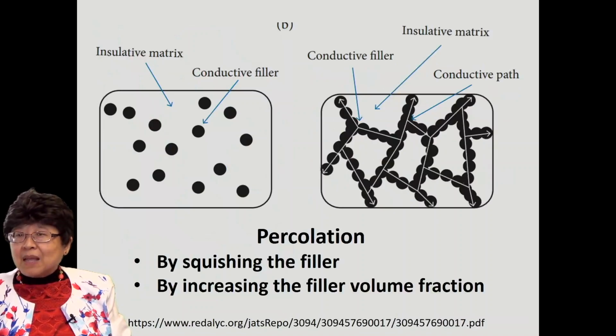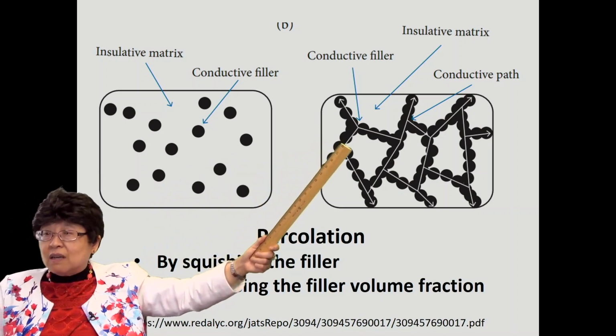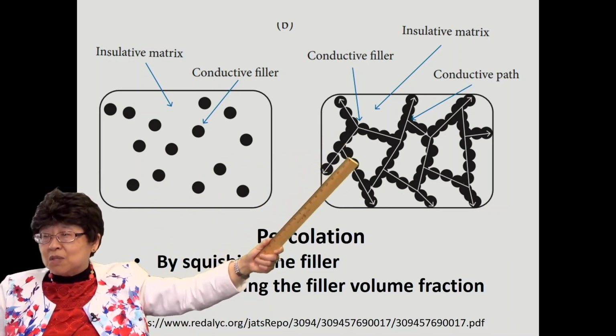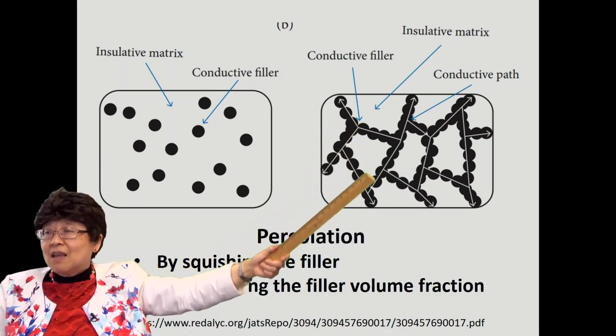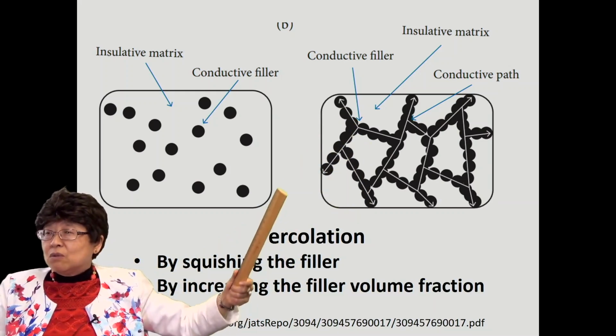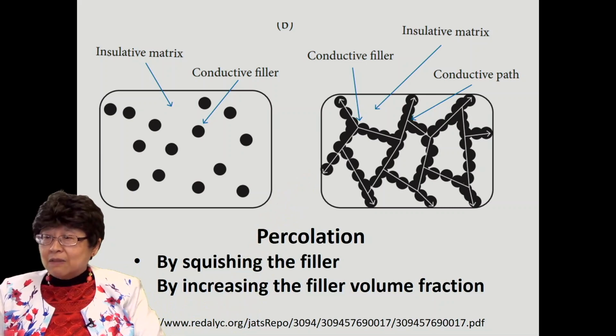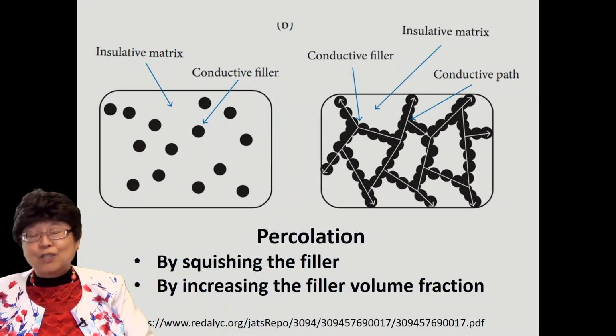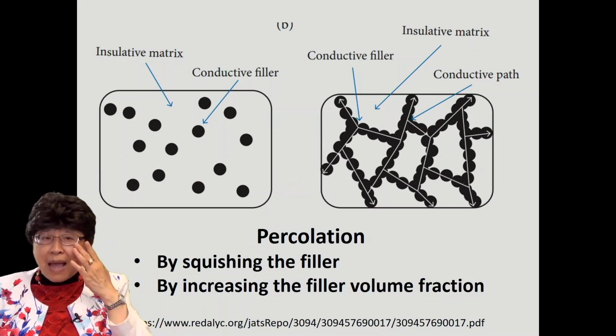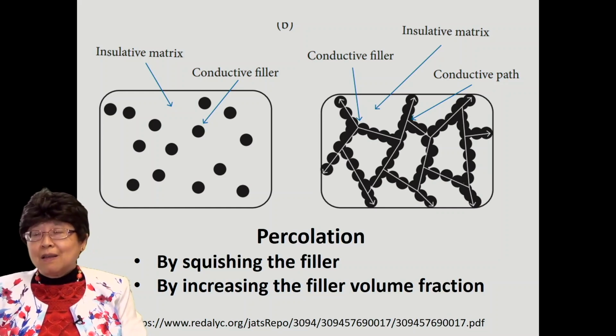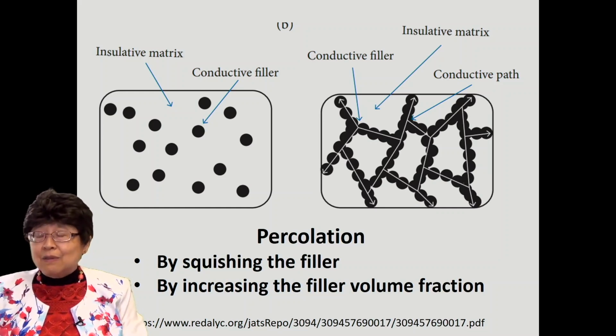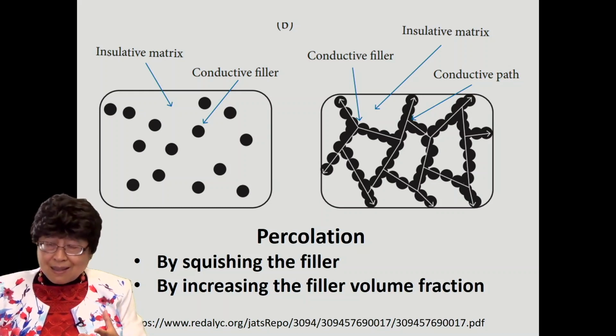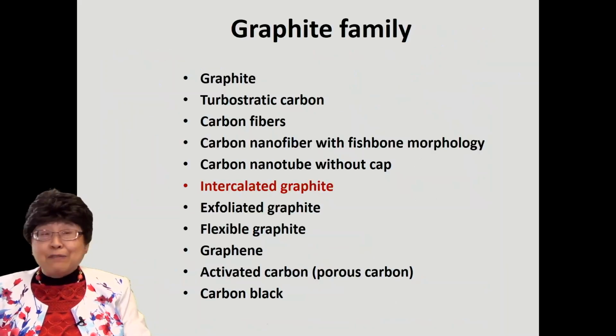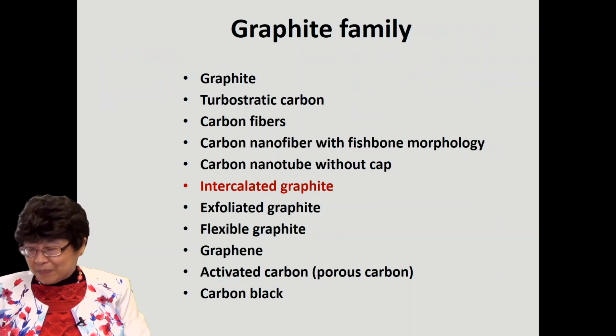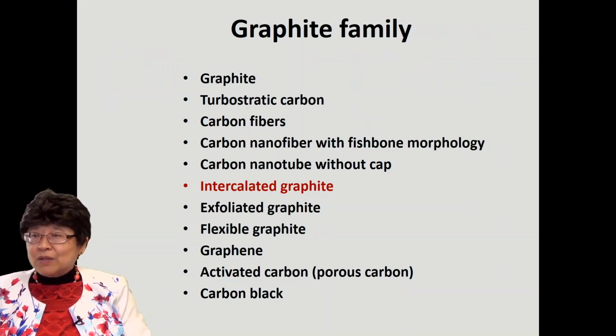And this is an illustration that after the squishing of the carbon black, it forms an elongated path like this. And that's called percolation. And so you have continuity in the electrical conductive path, and so you have good conductivity. So carbon black is actually very effective as a conductive additive because of its squishability. It can be even better than carbon nanotube in that regard. Next, we consider intercalated graphite.